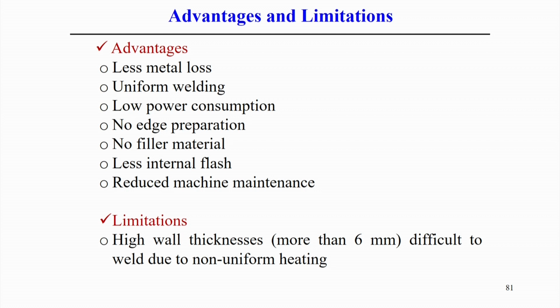Power consumption may not be very high, and no high pressure is required, because we create the arc, melt the surface, and only then apply the upsetting force. So, less material flash is produced, no filler metal is required in this case, and of course it also reduces machine maintenance.